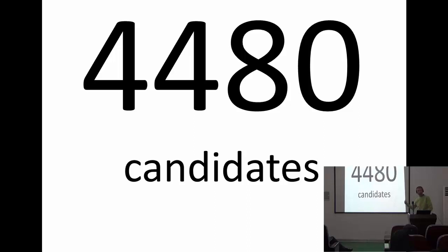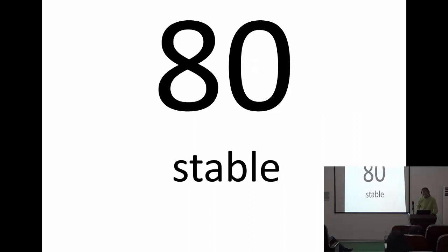That we do for all the 4,480 crystals that were in our set. And we find that 80 of them should be stable. So DFT predicts that 80 quaternary zintl phases in this search space are stable against any decomposition in binary and ternary crystals that we already know. It could be that there exists a ternary crystal that we don't know yet, and that would be a decomposition path for one of these. That's possible, but with the knowledge we have, that is the conclusion.